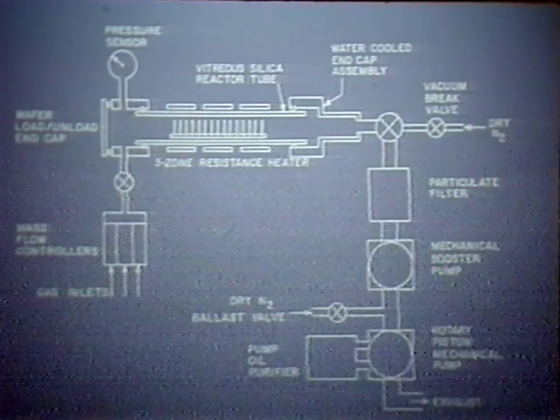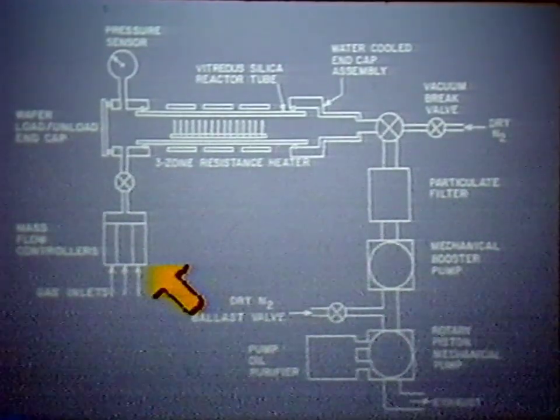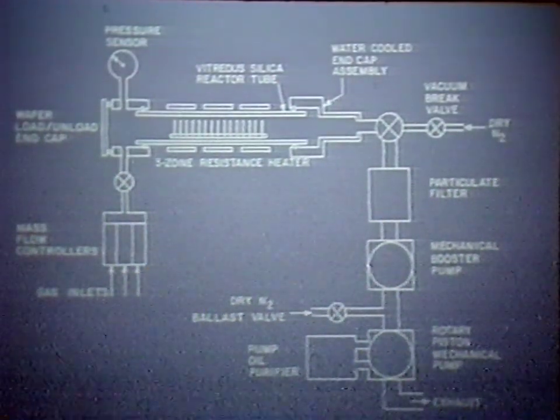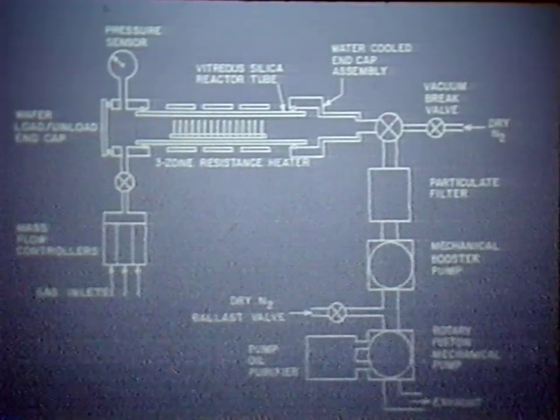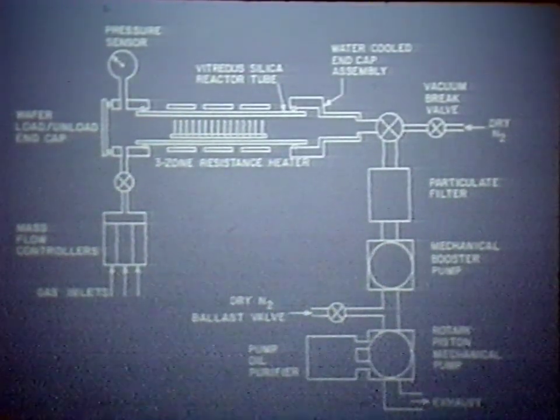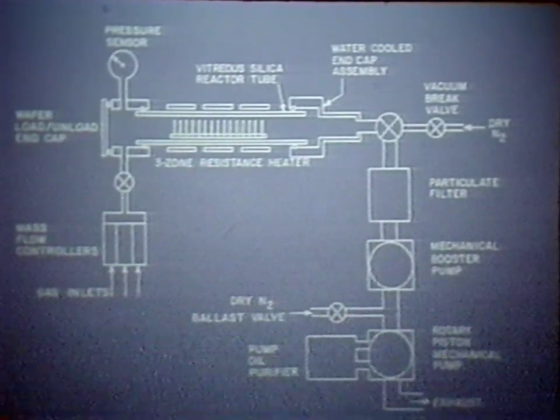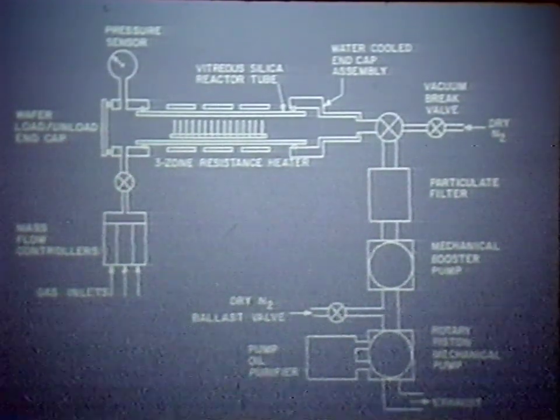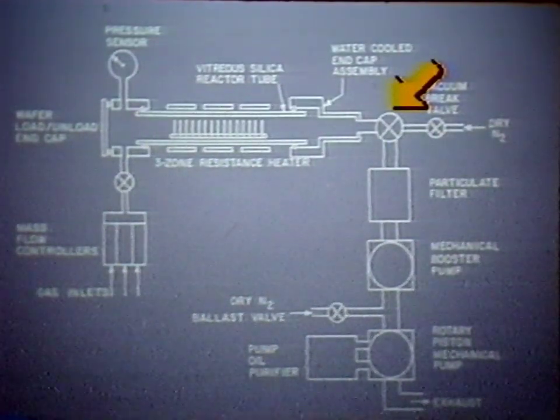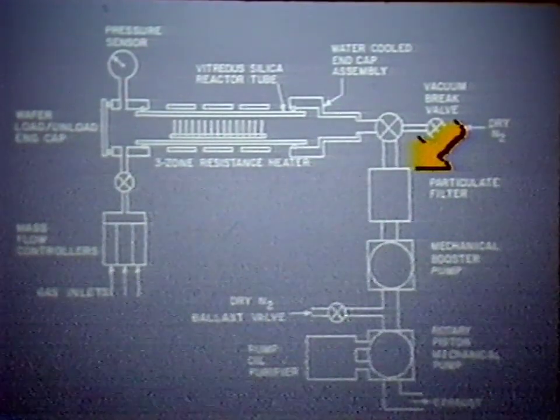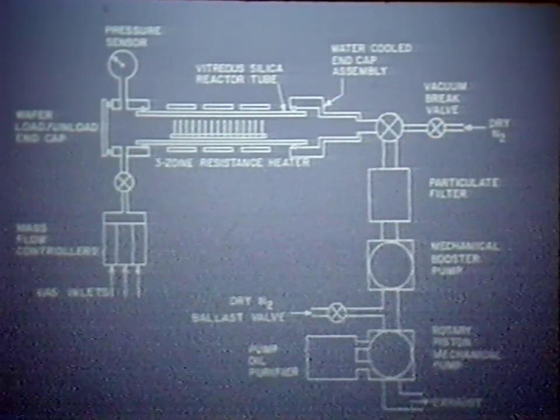And what we can see is that the gases are coming in, they are metered here, coming into the system. There's a pressure gauge up here to tell us the pressure of the reactor itself. Gases pass through the tube here and finally exit through the end here, where we have, first of all, a particulate filter to eliminate any contaminants so they don't get into the pump.